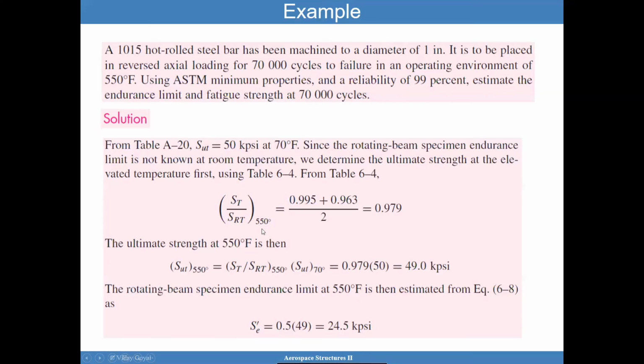And so knowing that information and knowing that it's 70 F, you can then determine that the ultimate strength at 550 degrees is 49 KSI. So it's not a big impact due to this temperature. The rotating beam specimen endurance limit will then be estimated assuming that it's basically half of this ultimate strength. So that's 24.5 KSI for the endurance limit in the specimen configuration.